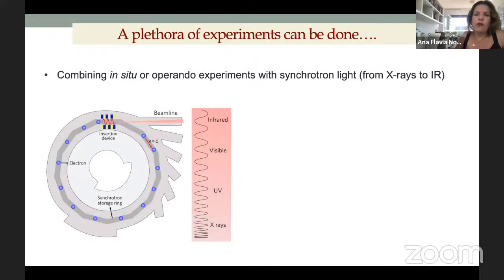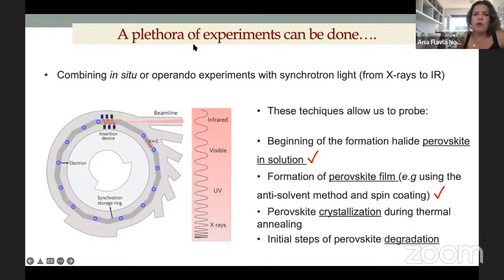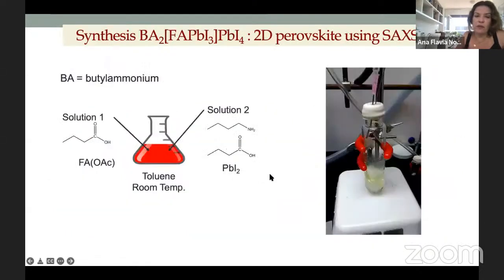So what's interesting for perovskite solar cells? If you couple in situ or operando experiments with synchrotron, you can, for instance, probe the beginning of the formation of the halide perovskite in solution. Also, you can follow the formation of the film. I'm going to show examples here when we track the formation in solution, and also the formation in the film using two different deposition methods. You can also follow the crystallization, which is really important to achieve high performance devices. And you can also track, for instance, the degradation. We have done all of these experiments at the beamline, but because of time, I'll just focus on the formation of the halide perovskites.